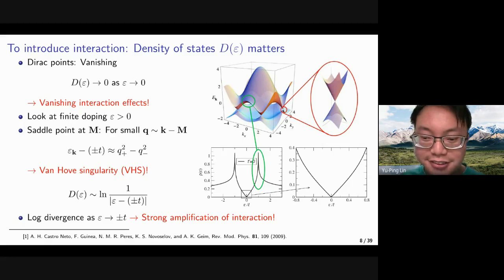That's a very good question because, as you have mentioned, it is somehow equivalent to the question that it is hard to really dope it into a finite doping regime. But I think recently people have found that with intercalation, one can indeed achieve finite chemical potential regimes. But now the density of states may not be logarithmically divergent. Instead, it will be power-law divergent, which realizes a higher-order van Hove singularity. That's another story, but a definite point is that they show intercalation to be an answer for doping to a finite chemical potential.